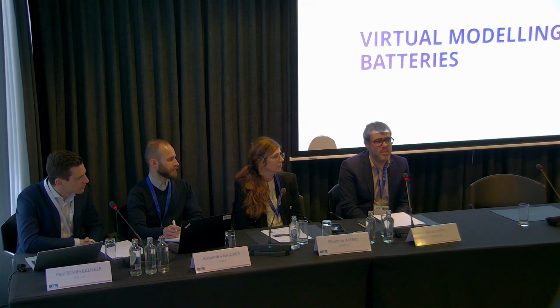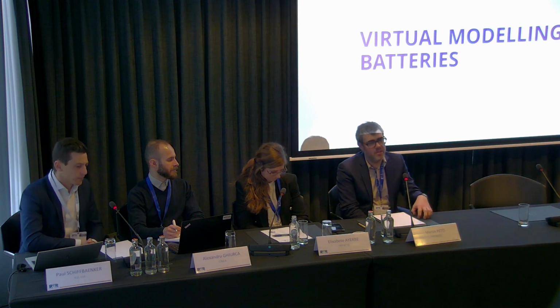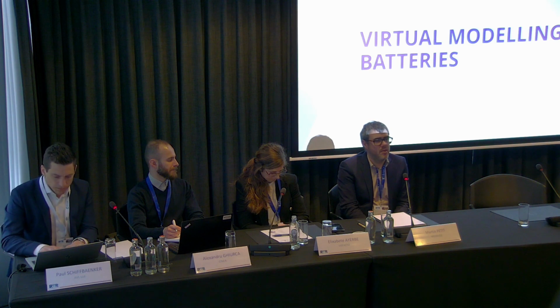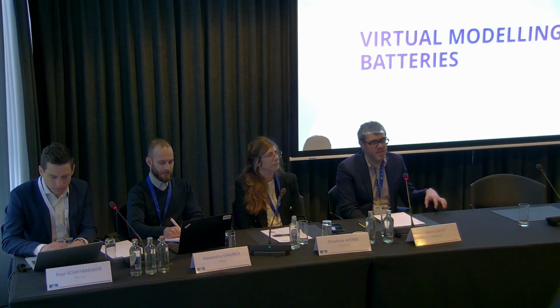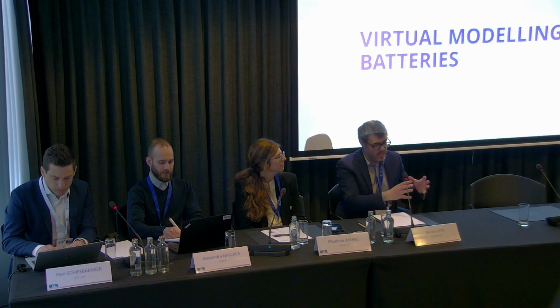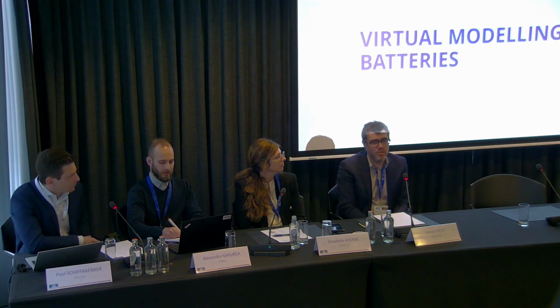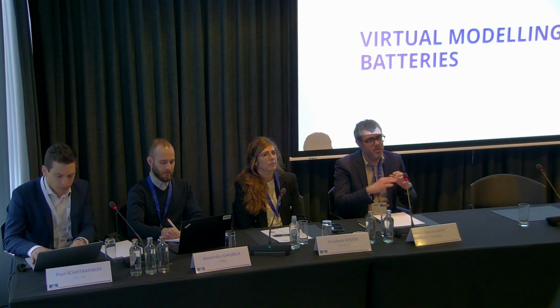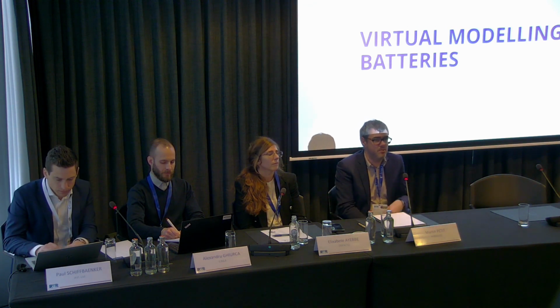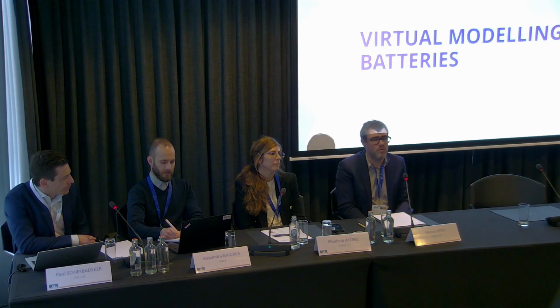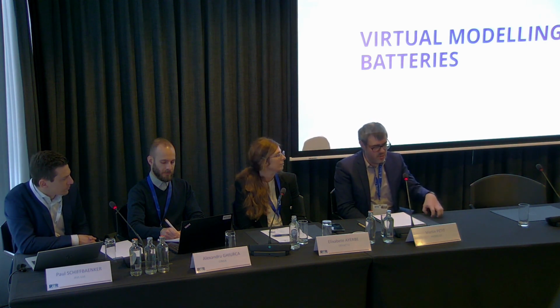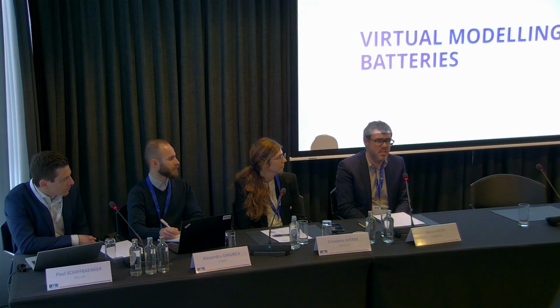In terms of pure modeling, one of the main difficulties that we faced as modelers, for instance, is upscaling for transport properties. When we use transport modeling for NMC, for instance, you want to go from the crystal to the full particles. It's a very big challenge because the particles are anisotropic. You have a lot of crystals, and the behavior is not the same as a pure crystal. And that's something that was not possible because we discovered it late inside the project, so we did not have time to go further. It was a huge challenge, and something that's still a challenge at the end of Modelis.